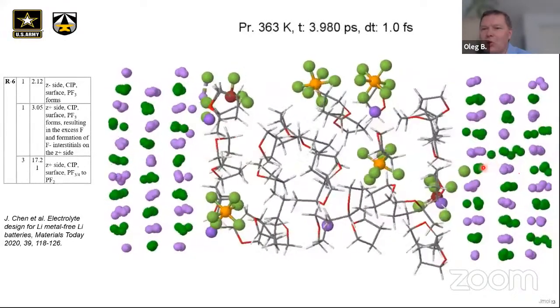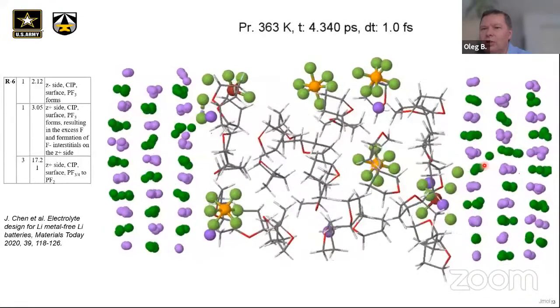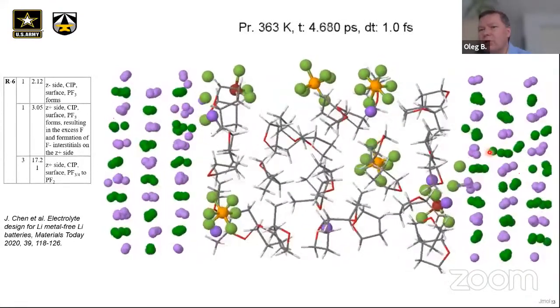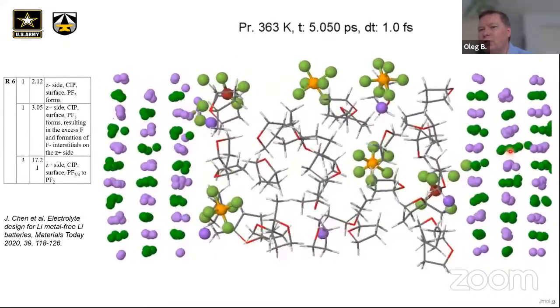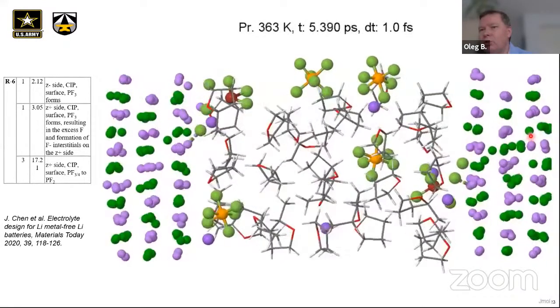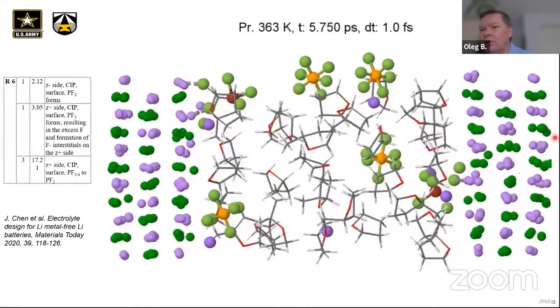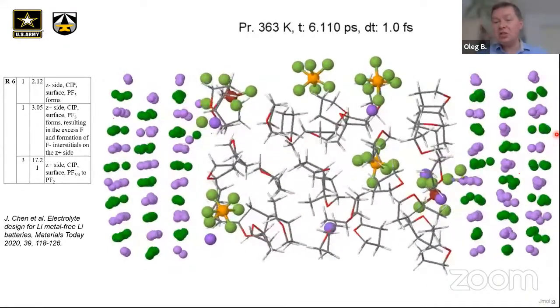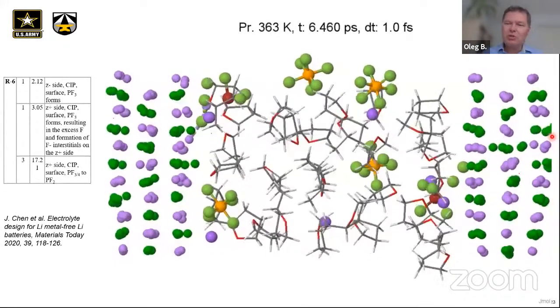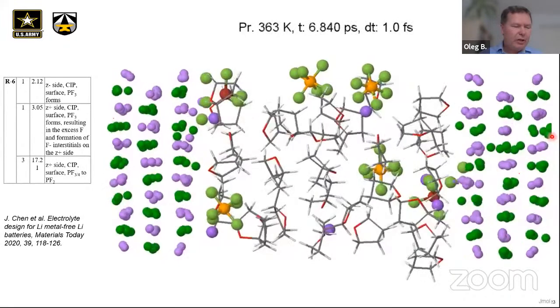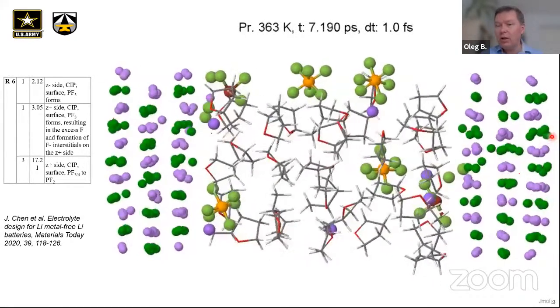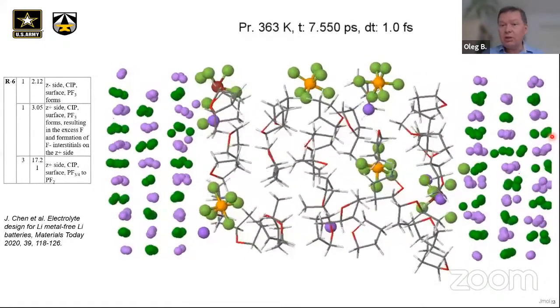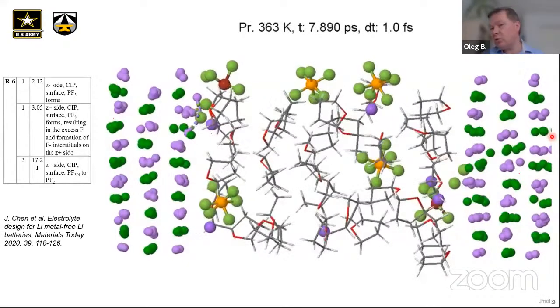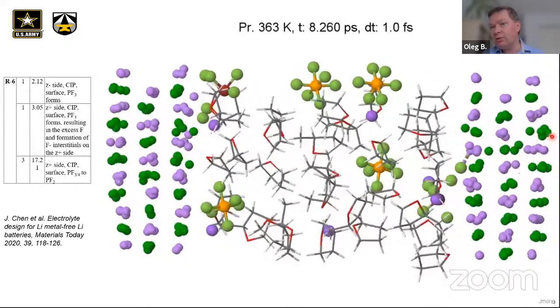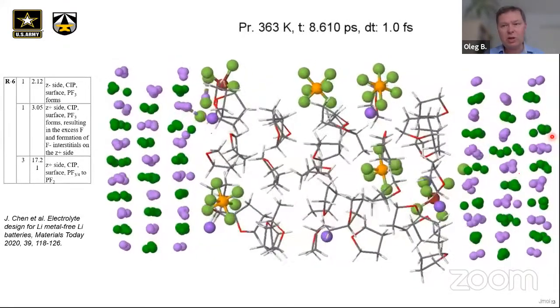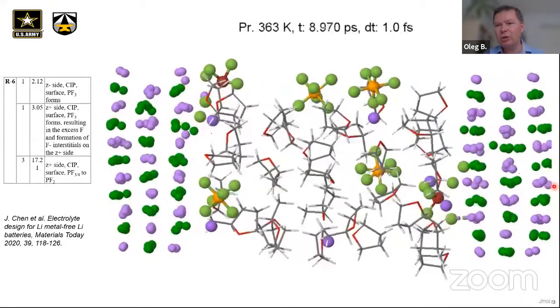Look at this fluorine. Once this fluorine comes in, it starts kicking out and makes an interstitial fluorine. This interstitial fluorine wants to go to another layer, and once it's going there, it's kicking out and putting another fluorine to the other side, and there is LiF eventually forming on the other side. I think that's a very interesting insight, because the majority of groups had a very hard time understanding why LiF is good, why LiF has reasonable lithium conduction, while it is expected to have very, very low conductivity because it has a lithium vacancy diffusion mechanism. And of course, if you're next to the lithium metal, you don't have many of those.